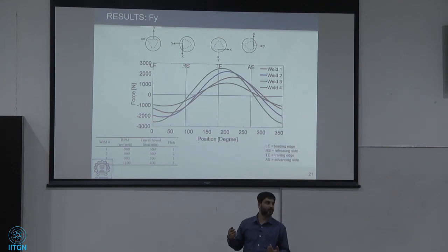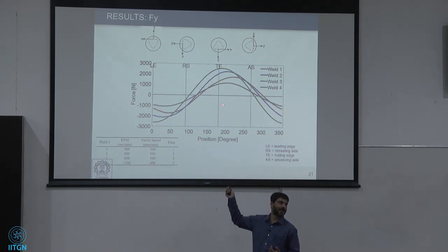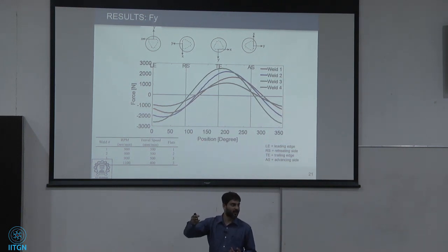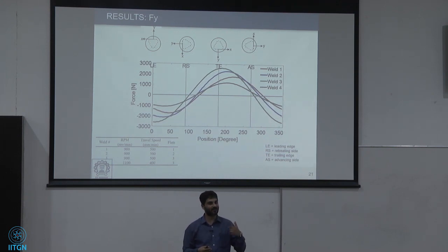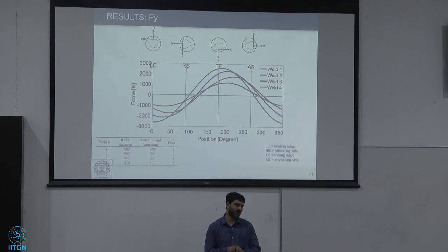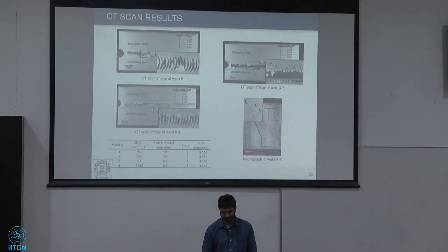And what's that going to do? That will end up increasing these compressive forces rather than taking them to the positive side. So this again bolsters the hypothesis that there is a defect, there is a cavity which forms once per revolution and gets filled in the process.